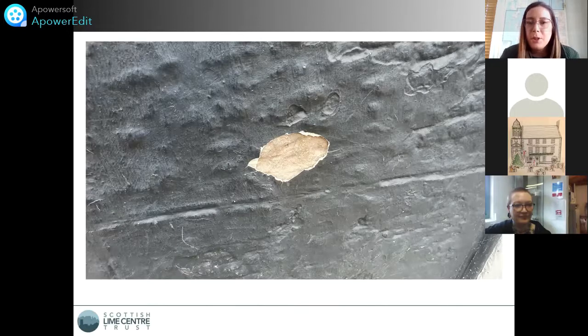And this evidence of lime washing is good for justification for redecoration, and we'll come onto that in a little bit. But if we left it unrefurbished, what is happening is all the water that hits the face of the wall is concentrating in that little hole, and it's concentrating all the water into the stone, which is porous, and it's sucking it up, but it's not really allowing it to dry out. And so what that results in is a constant washing, constant saturation of the stone, and the stone goes through a lot of washing and salt crystallization, and basically what ends up is the face of the stone basically disintegrates.